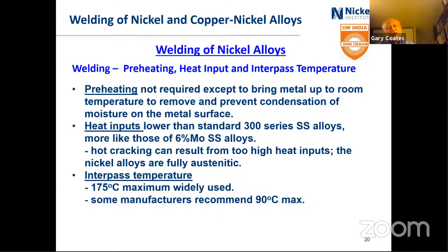The interpass temperature, some people say 175 Celsius as an interpass temperature for most alloys. Others are conservative and say 90 degrees C. And I've always favored, if you say 175, the welder, chances are he's going to say, well, that's close enough, I don't need to worry about it, and maybe it's 250. So we usually like to say 90 or 100 degrees C maximum interpass temperature.